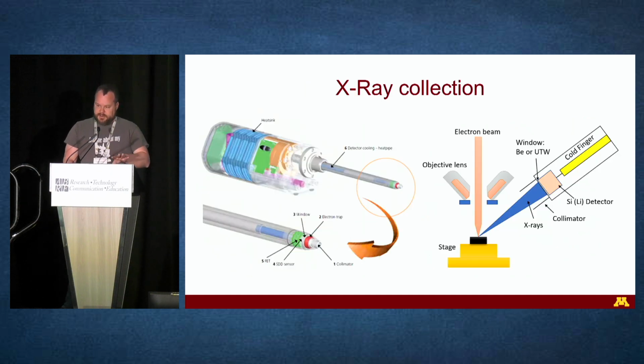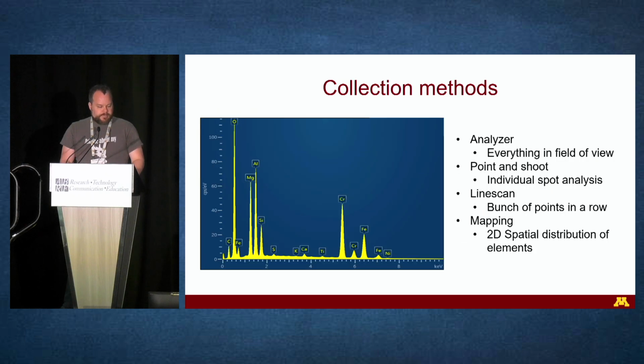You can generate pictures and spectra of the chemical distribution in your material. The actual detectors themselves are relatively simple. There's a silicon lithium detector. It's kept cold, typically these days just by a Peltier cooler, but in the past with liquid nitrogen. And they simply point at the sample and they just collect the X-rays that hit the detector. And the computer combines that with the position of the beam to give you where the chemistry is coming from.